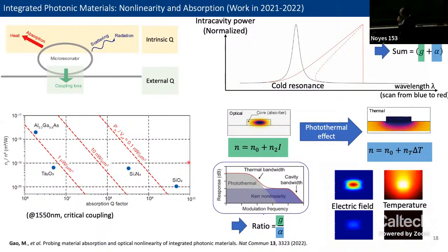For example, the widely used material silicon dioxide, silica, is right now widely used as a cladding material. One main reason would be its low loss, and also its lower refractive index. Another extreme example is aluminum gallium arsenide, which is a semiconductor material. Semiconductor materials are typically well known for their high nonlinearity.